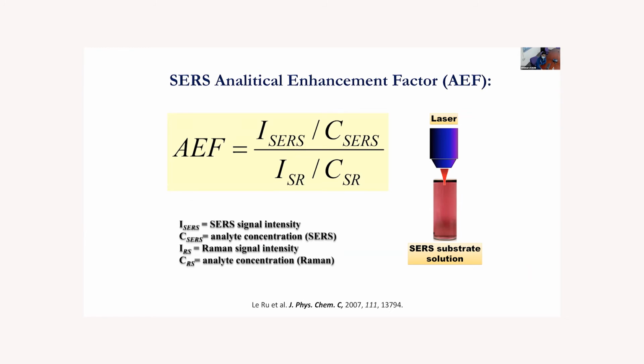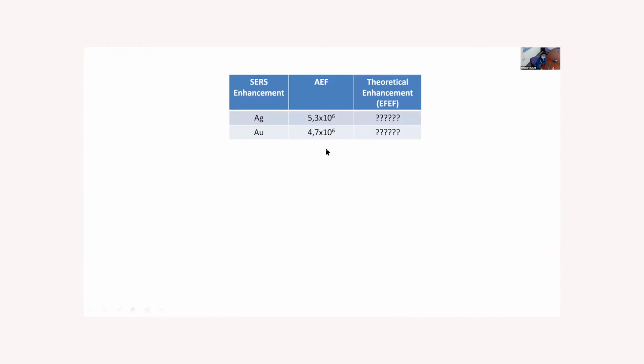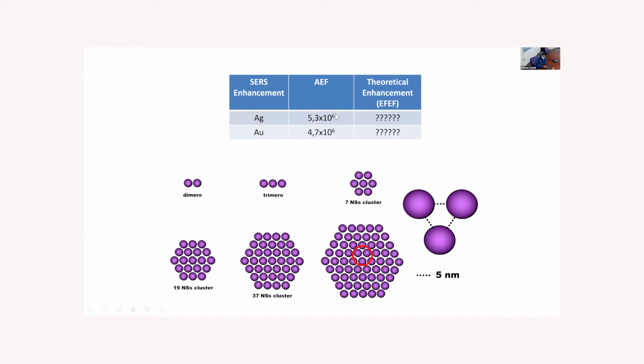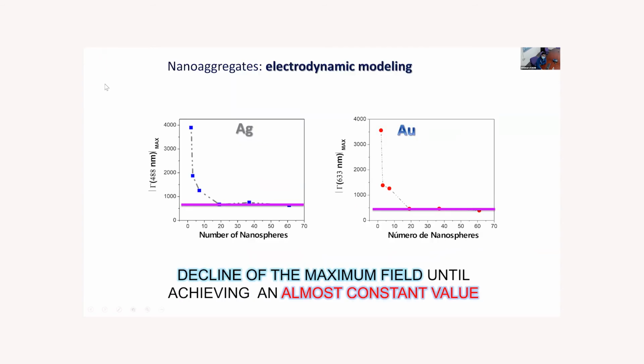From the Raman spectra, from the SERS spectra, we can calculate the analytical enhancement factor, and then we will correlate this data with some simulations. We get this kind of enhancement, 10 up to 6. And we developed a 2D model in order to model the results. What we found was that if we graph the enhancement as a function of the number of spheres, in the case of silver and also gold, we have more or less the same result.